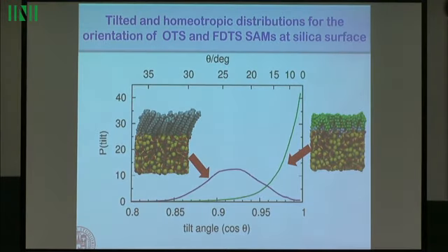We tried to look also at a condition for inducing, rather than planar alignment of a liquid crystal or a functional material at the surface like we had before, alignment perpendicular to the surface, which is called homeotropic. In practice, people have used molecules similar to this, lecithins, which have two chains rather than one, or even this self-assembled monolayer to induce perpendicular order. But this is strange, isn't it? If you use this and it is tilted, why should you get 90 degrees if you start with a surface which is combed in this direction, which is pre-tilt?